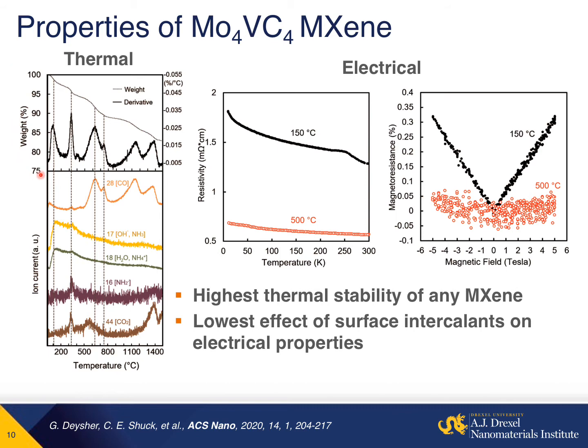With MXenes, what you typically see is a release of the adsorbed water that's intercalated between the layers, followed by degradation and release of the delaminant used. What we saw is this occurred well below 500 degrees for this MXene. However, this MXene, so this two-dimensional material, was stable up until about 800 degrees Celsius, which is higher than any other MXene studied to date.